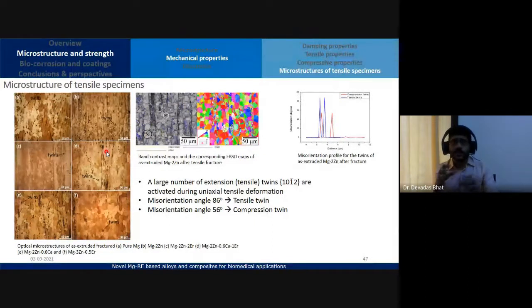Because it works something similar to that of your grain boundaries. Okay, grain boundaries, they act as physical barriers to the corrosion attack. Similarly, the twin boundaries also act as a physical barrier to the corrosion attack. Okay, so the activated twins here also increase the protectiveness of the surface films, and it suppresses the microgalvanic or microcorrosion couples occurring in the twinned grains here.